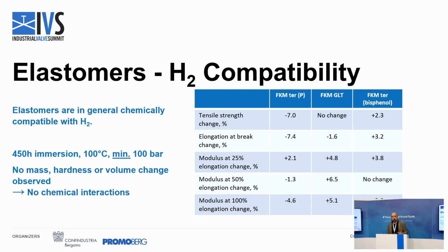And after 450-hour immersion, this does not have any special meaning. It's just that we ran the test and then we presented this work in another place. So we have data for 450 hours, but still it's 19 days. So it is more than enough to say that the chemical interaction and the loss of mechanical properties of the elastomer is basically zero. So this is another proof that hydrogen will not have any chemical or aging effect on the elastomers.